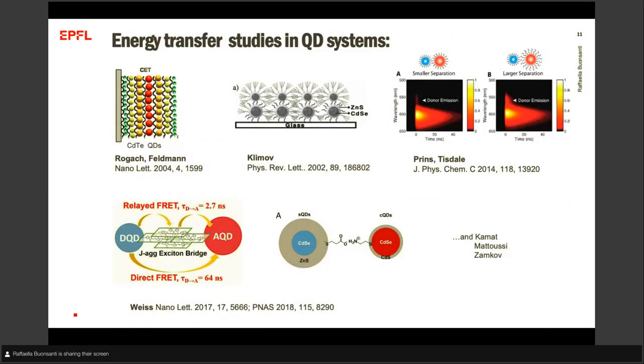Now, there has been beautiful work in the literature on energy transfer with quantum dots. In many of these examples, the spacers were actually organic ligands or organic moieties of some sort. And there are two issues with these organic ligands. One is that the tuning of the distance between the quantum dots is kind of limited, because we cannot go to really big distances, because the carbon chains are quite mobile, and it's difficult to keep the distance between the quantum dots constant. And especially in the case of the perovskite, these organic ligands will not protect the perovskite from degradation.